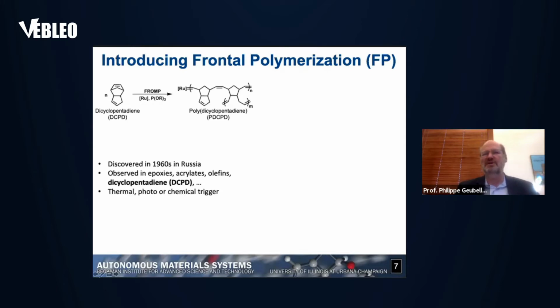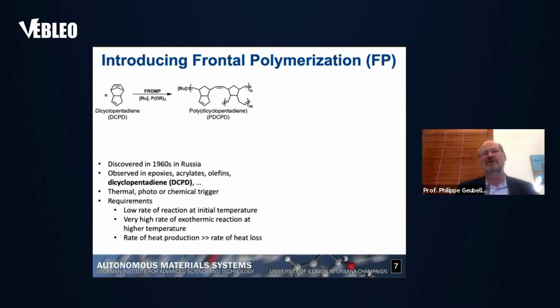And it can be triggered in different ways, right? Most of what we do is thermal, but we've also done photo or chemical triggers. The key requirements to have frontal polymerization is you have to have a low rate of reaction at initial temperature, so you can go through the manufacturing process, set up the part that you want to make, and then once you introduce the trigger, you want to have a very high rate of exothermic reaction at higher temperature in such a way that the rate of heat production greatly exceeds the rate of heat loss. For those who are interested, I recommend a very nice review paper by John Pojman, who's at LSU, Louisiana State University, in Polymer Science in 2012.